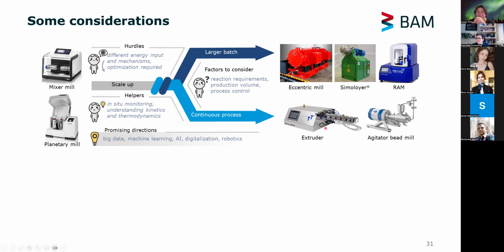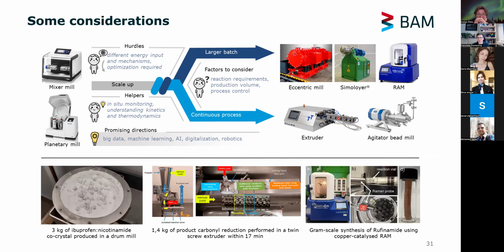So, and these extruders are things that are, at least for the moment, of most interest. But just to show you, you can see here these colleagues from the MPI went up to make 3 kilograms of a co-crystal in this case, just in a larger mill. Okay, going back to that, here what we focus on is using extrusion in our lab, and this